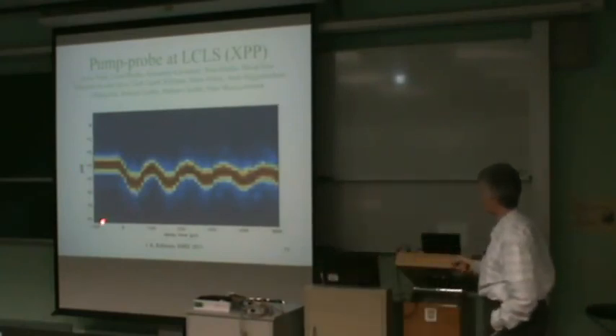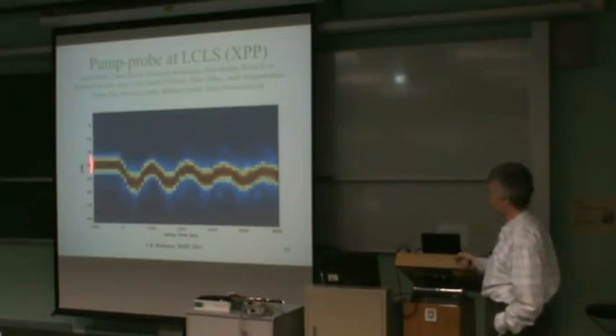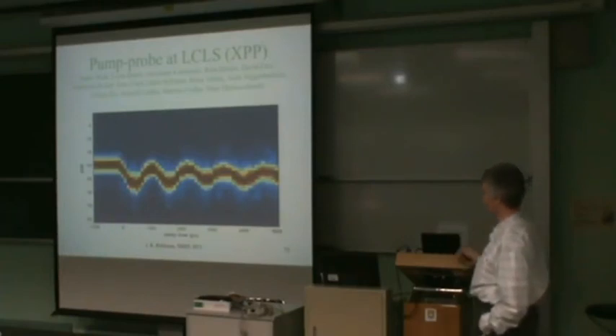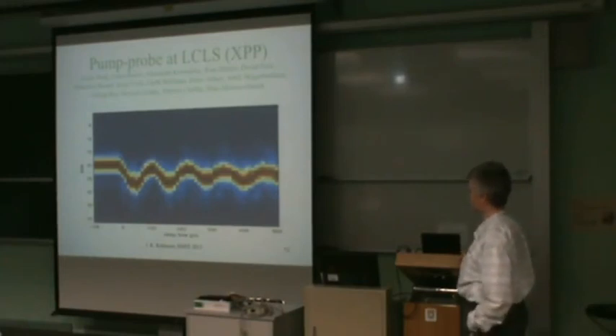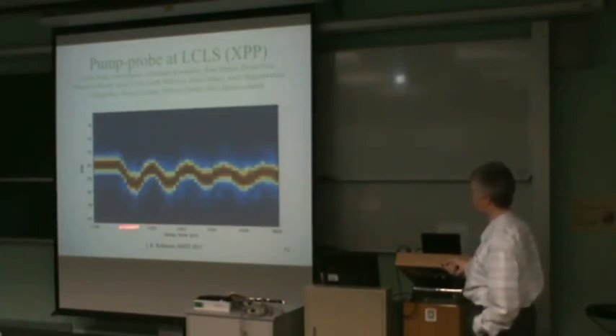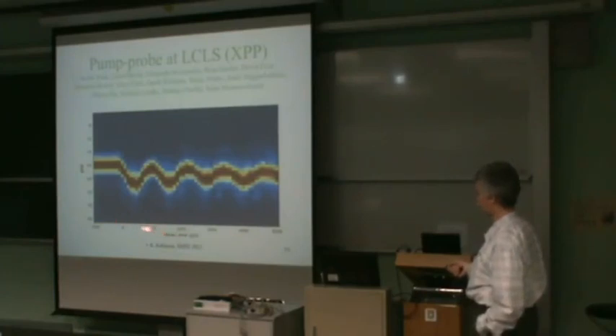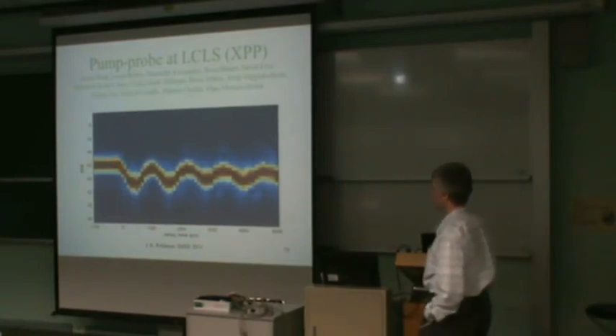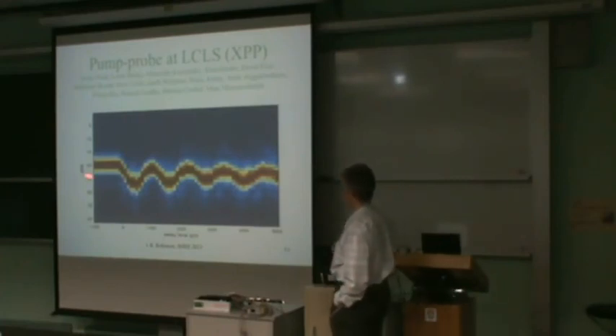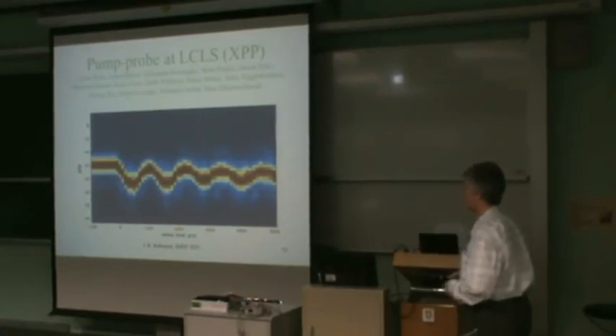So we're expecting to see a compression wave, but what we actually saw was a Bragg peak. This is the 2 theta value of the Bragg peak as a function of delay time, and this is the time delay between the excitation with the Ti-sapphire laser and the X-ray laser, which are both femtosecond long pulses separated by a time in the range of picoseconds here. And what we see is a drop of the Bragg angle of the Bragg peak of the gold, indicating that the crystal is expanding. So that picture I just showed you is incorrect.